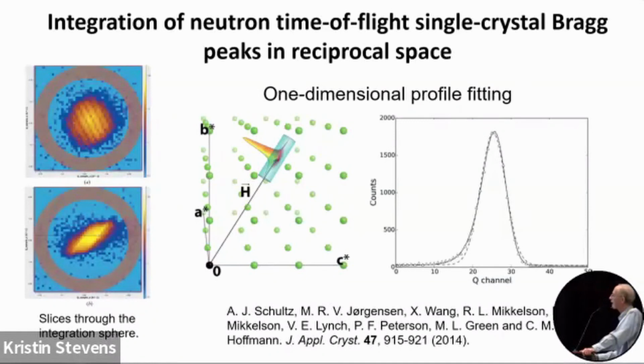So one of the analyses we did was to test and analyze what's the best way to integrate the Bragg peaks. And the major finding was that we get much better results if we map the data into reciprocal space and then integrate, rather than trying to integrate in detector space on the detector themselves. And so then in reciprocal space, I think we get nicer shaped peaks, so it's easier to integrate.